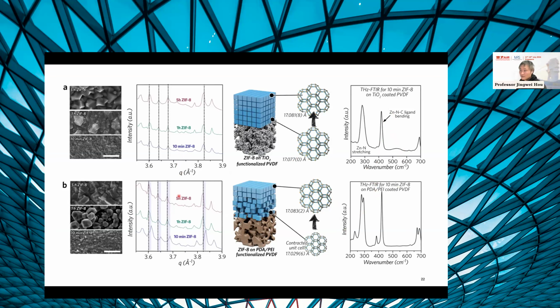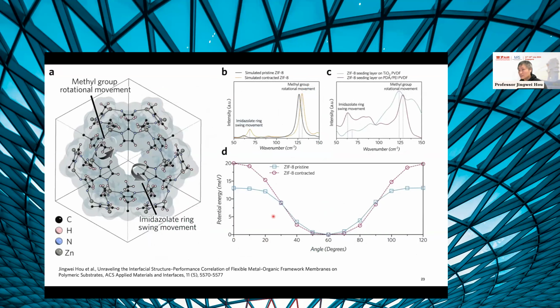After we had done the refinement, we found, okay, for the ZIF on ZIF-8 crystal, it's pretty much consistent. The crystal structure is reasonably consistent. But for the dopamine surface, it seems like the crystal is getting smaller. By how much? It's only by 0.3%, so that's not much, right? But once we put the model into a dynamic structure, it looks like a 0.3% change in the lattice parameters will significantly make the framework much more flexible. That is something really bad for a membrane, because for a membrane, we want something rigid and tough, but it seems like the polydopamine can make the material more flexible.